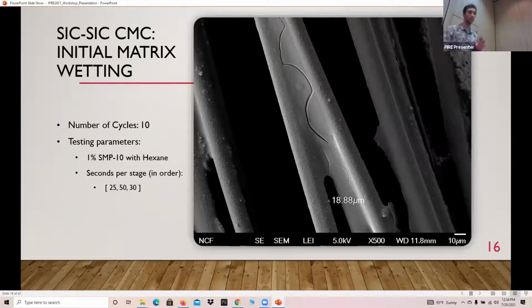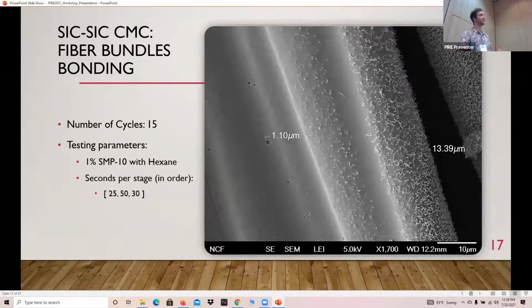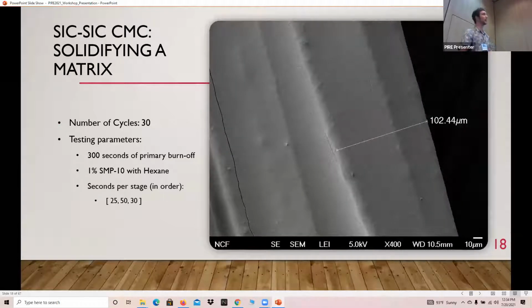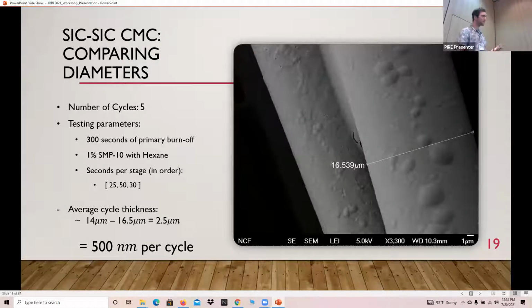Here is just some initial images of the 500 nanometer setup, so 1% SMP10 with hexane. Total number of cycles on this one was 10. And then here at 15, we can see we're actually building up a pretty uniform dense matrix. And then here at 30 cycles, we have a somewhat fully dense microcomposite after those 30 cycles. So if we analyze a little further, we can see, again, that's 500 nanometers per cycle.